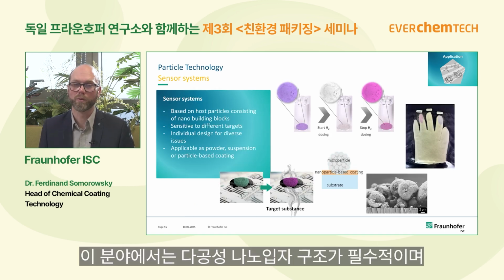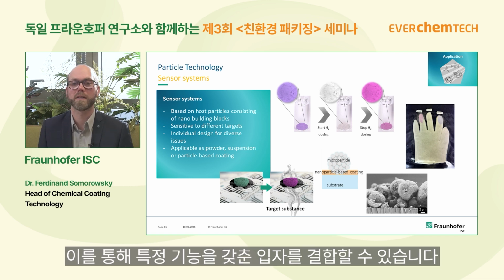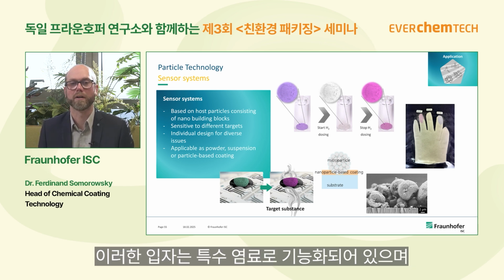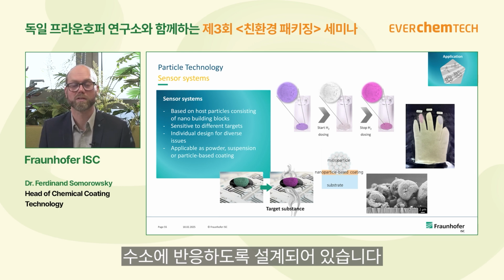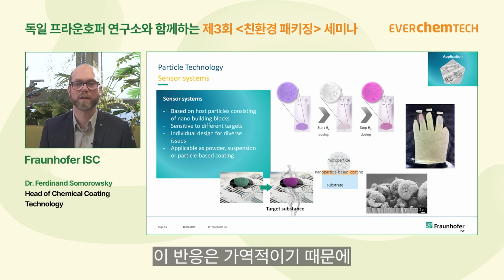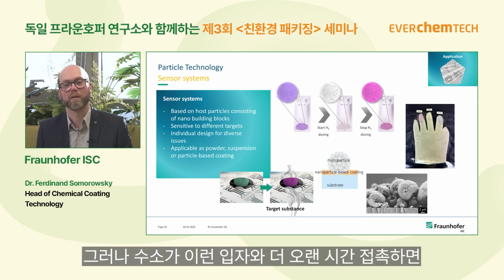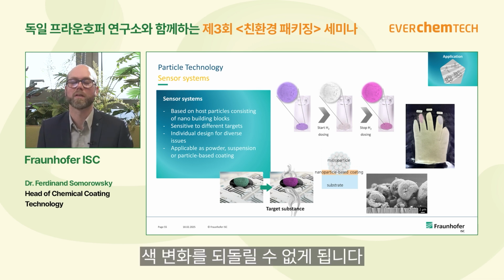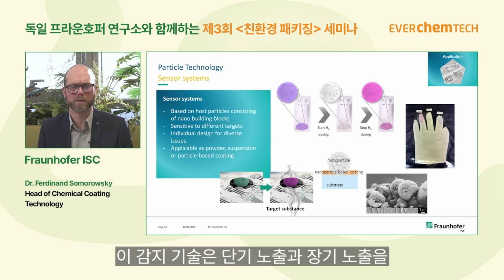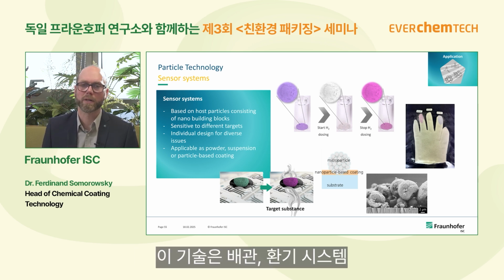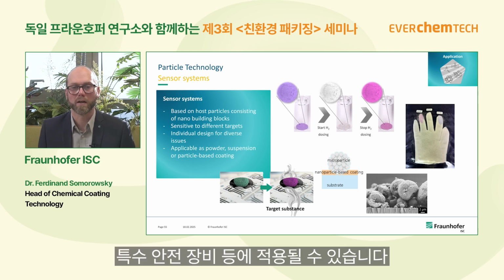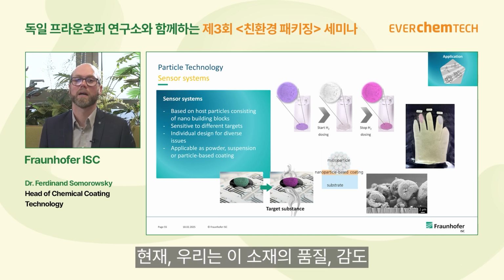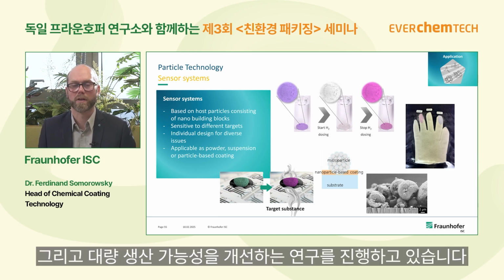Sensoring plays an important role, and here we need this particle base because of this porosity structure to integrate the particles. The particles are functionalized with a special dye which is sensitive towards hydrogen, for example, and with a small contact of hydrogen the color changes. This is reversible, but when the hydrogen works for a longer time and the duration is longer on these particles, it's not reversible. So you can really have a sensoring for a short contact and also for a longer contact. The application here is, for example, on tubes, on fan tiles, but also on special safety equipment. And we are improving at the moment the quality, the sensitivity, and also the upscaling of the material.